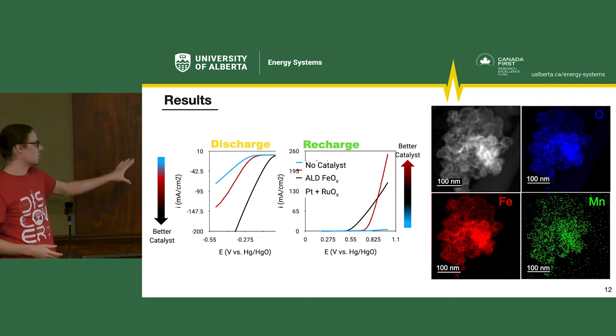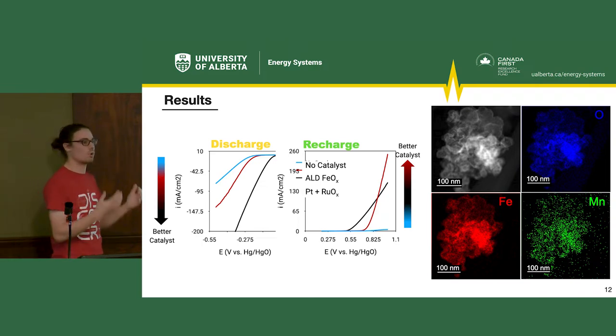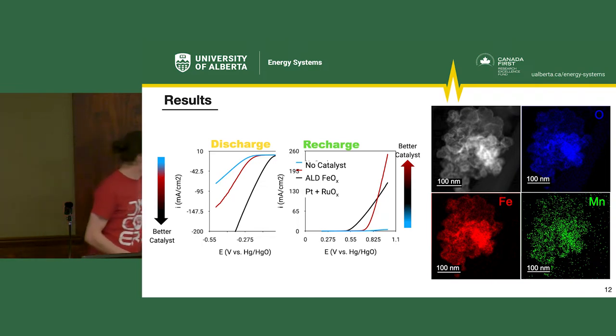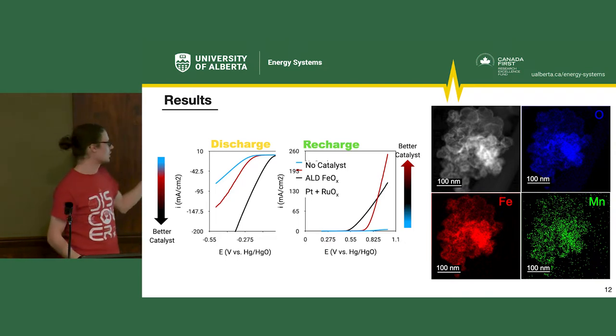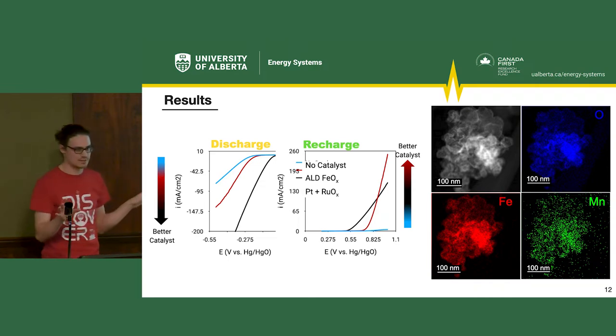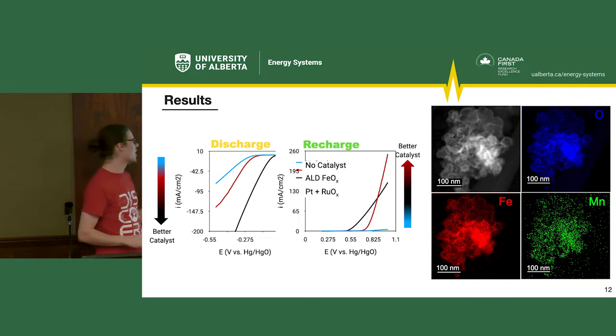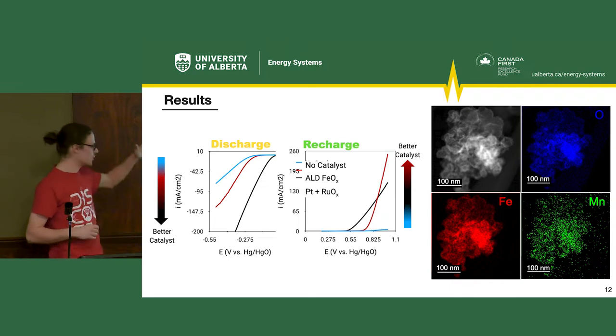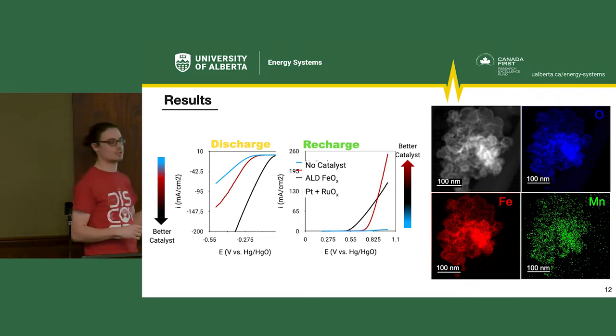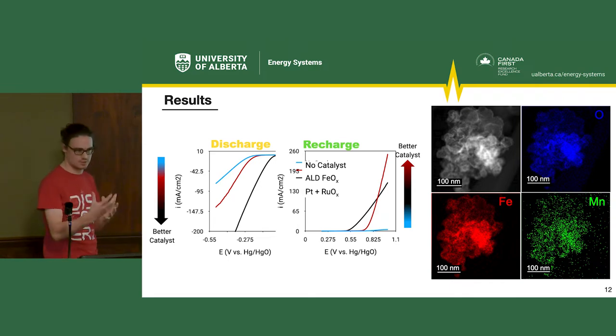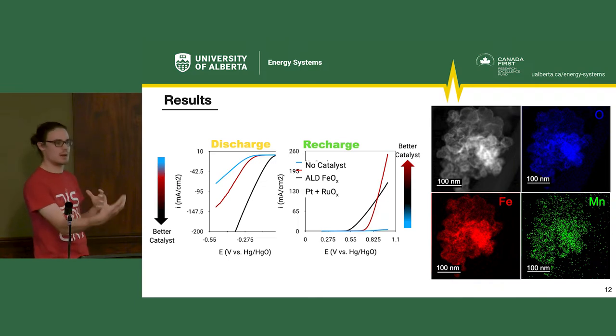And in this test, we're looking to get more current with lower potential. So we want to get kind of right here would be perfect, but the closer to the right, the more current we can get, better. So we're looking at blue is just nothing, just no catalyst. Red is my iron oxide. So we've improved our current with lower potentials. So we're getting better efficiency in a certain sense. The reaction is speeding up.